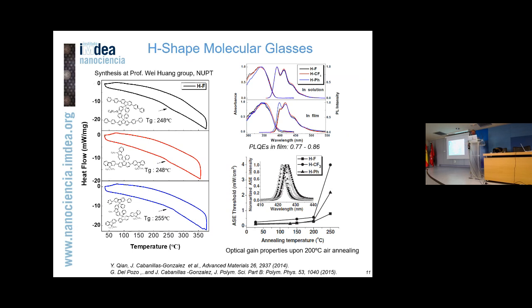triplets, polarons, I mean charges. When you inject charges in these systems, they lead to polaron absorption. So if you do engineering and design materials that have this absorption shifted away from the stimulated emission, then you can have some chance. But otherwise, it's really difficult.